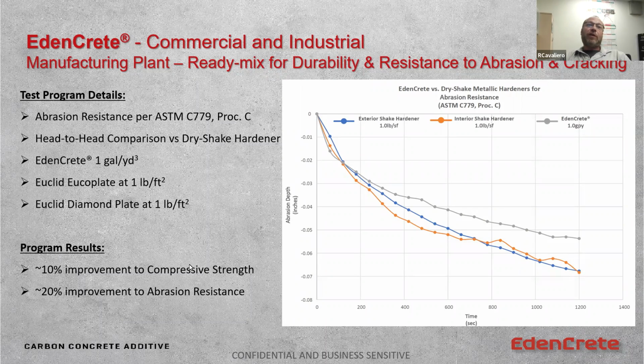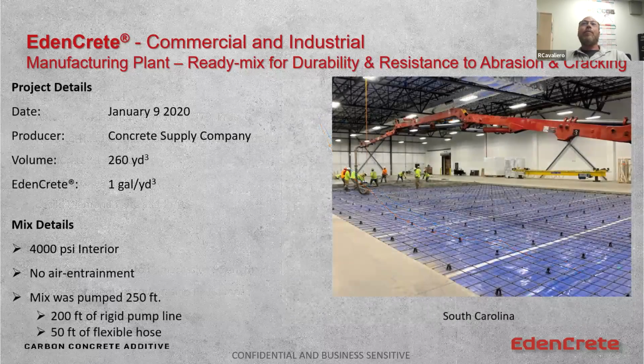Remember I said compressive strength. It might be there, it might not. Less than 10% compressive strength is 0% improvement in my mind. Here we had a 20% improvement to abrasion resistance with a 0% improvement to compressive strength. Conventional wisdom has said better abrasion resistance, harder concrete, right? And that's not what's going on in the world today with nanoparticles.